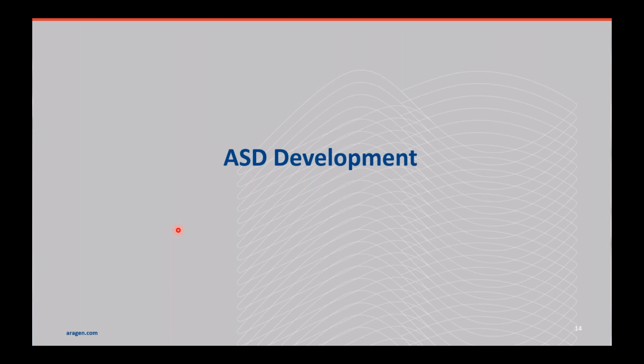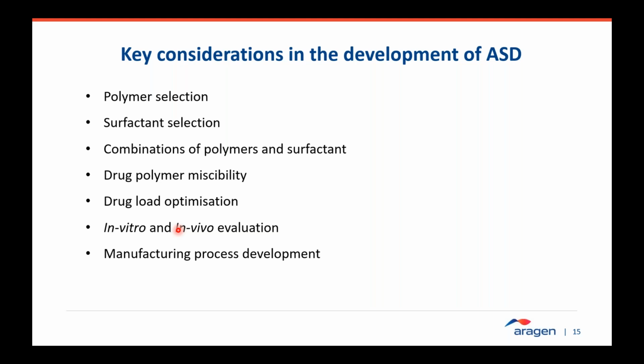So in the next few slides, I will take you through the development process, how ASD is developed typically in the industry. The key considerations in the process of screening, scale-up, and process development start with the polymer selection. In the second step of screening, we select a combination of polymer and surfactants, and we evaluate drug polymer miscibility of the selected polymers, and we need to optimize the drug loading, usually between 10 to 40%. 40% tends to be the upper limit where we can achieve a stable solid dispersion.